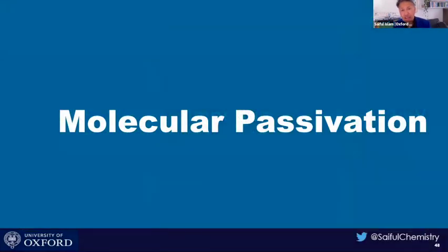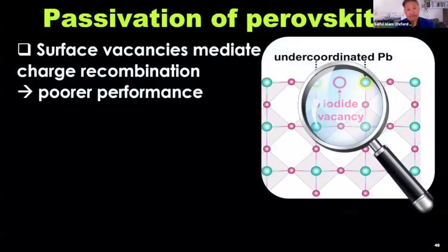So this leads on to, can we passivate these defects for improving their stability using molecular passivation? So what is molecular passivation? On the right, I'm showing you a schematic of a surface of a halide perovskite where there's an iodide vacancy at the top. Can we passivate that? The reason we need to passivate it is those vacancies mediate charge recombination, which we don't want. And that leads to poorer photovoltaic performance as a solar cell material.